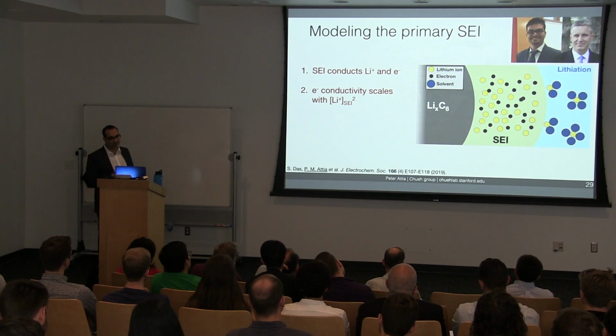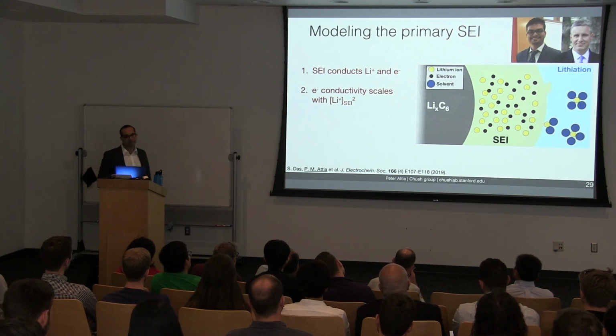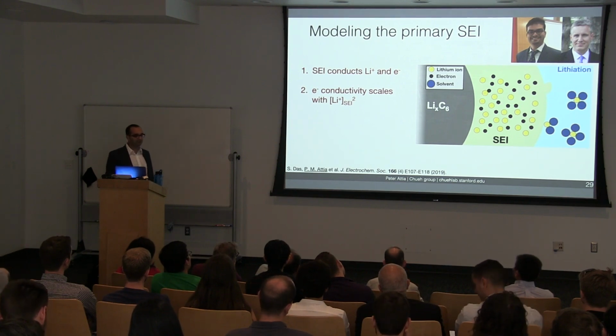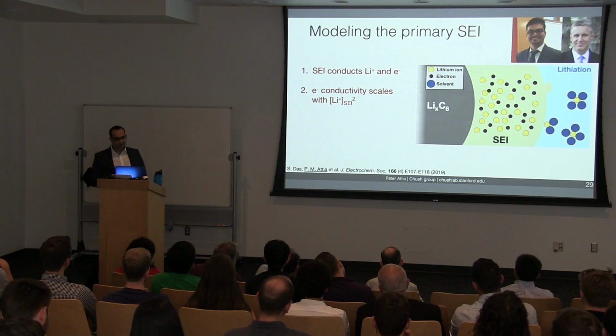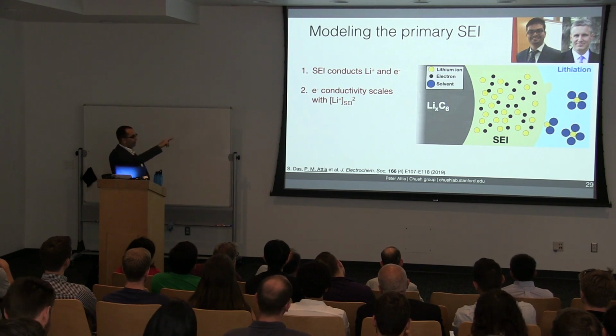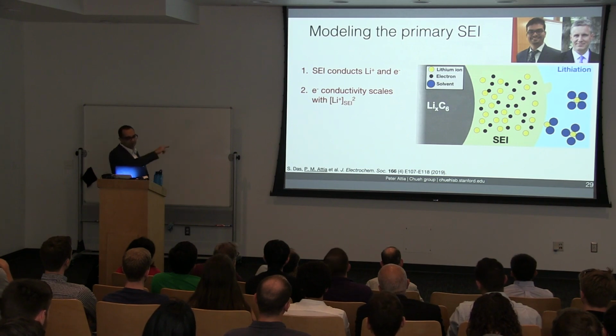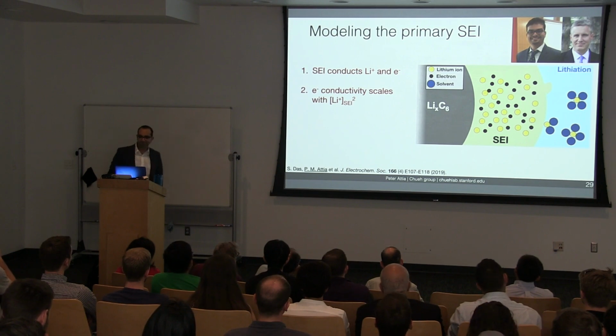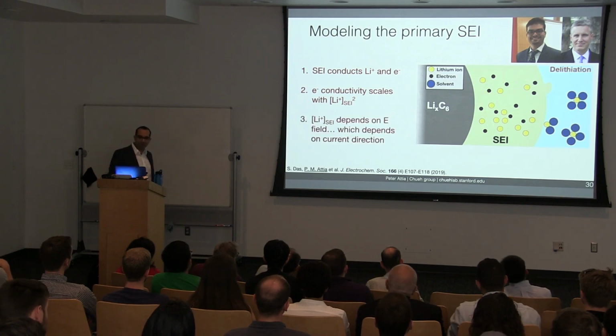The second assumption is that the electronic conductivity of the SEI scales with the square of the lithium ion concentration in the SEI. Now we know that the electronic conductivity must be highly sensitive to the ionic concentration, so we build in the square dependence. This is actually a pretty standard assumption in semiconductor physics. Now the electrons are localized with other electrons as they move across the SEI. The technical term for this is actually hopping. So once the electrons hop across the SEI, they react with solvent and lithium ions to form new SEI. So now we have a mechanism for the electronic conductivity to change.